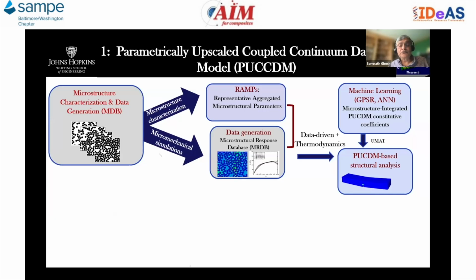I'm going to try to move through this a little fast because it's quite elaborate, this process. So this is the generation of these methods. We first, from the microstructure, do characterization and data generation. From that, we generate the ramps, the representative aggregated microstructural parameters. And then, from the evolution of deformation, damage and electrical fields, we generate this microstructural response database. And then we use data-driven techniques plus thermodynamics.